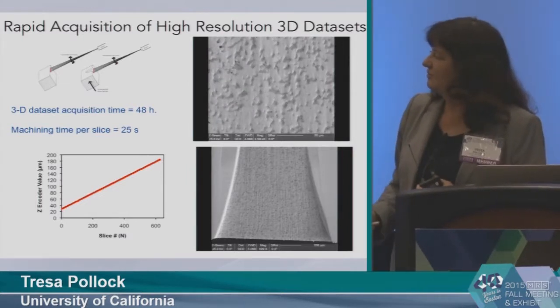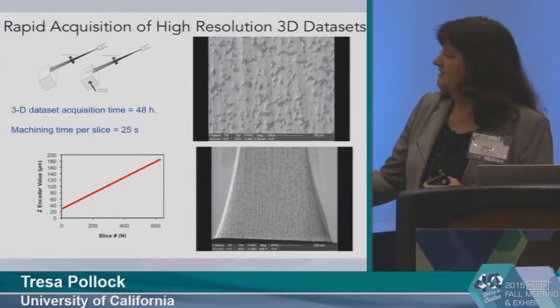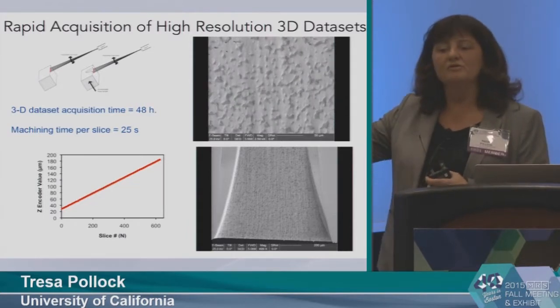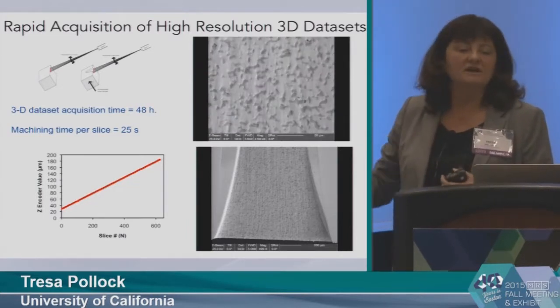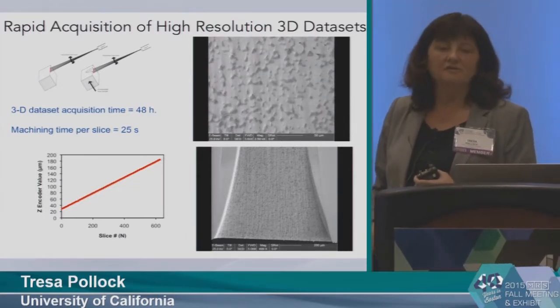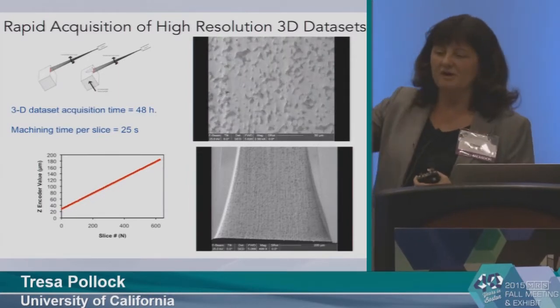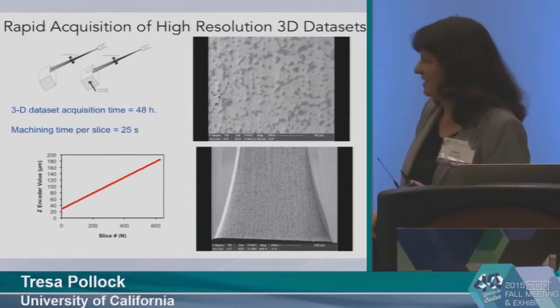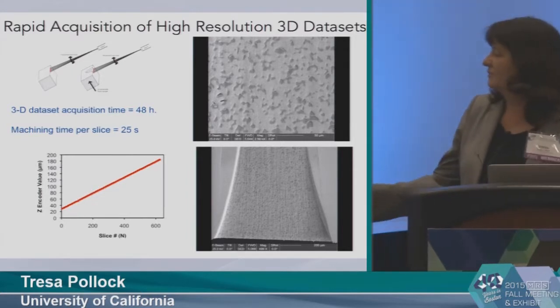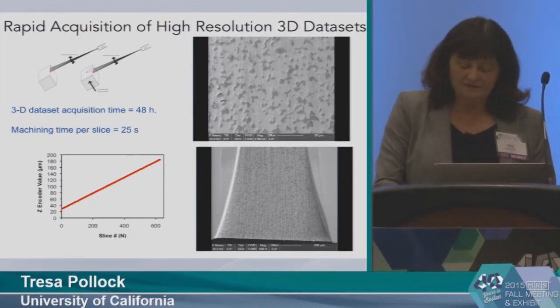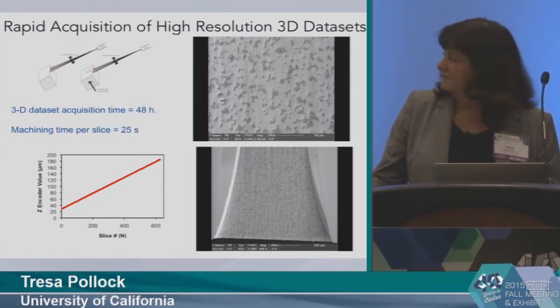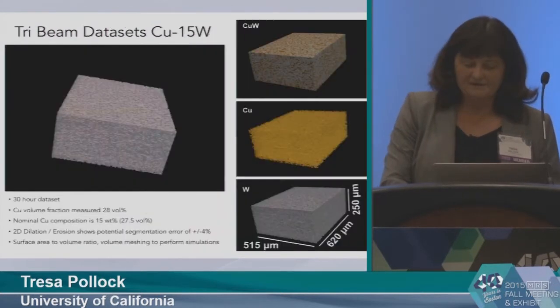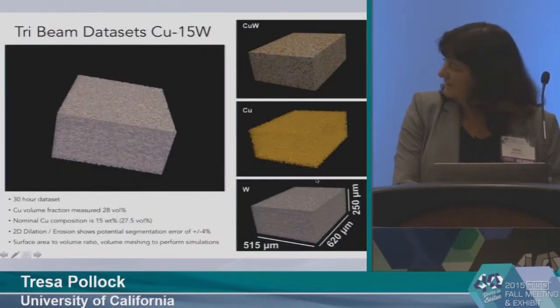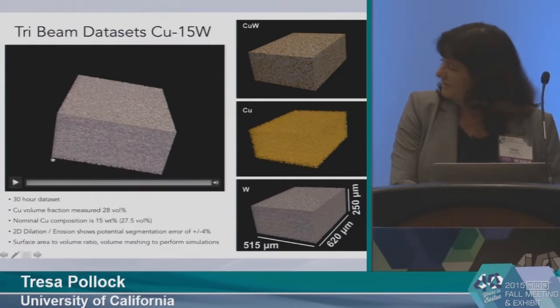You can see a few voids here. And basically, the material removal is now free. It takes a few seconds to remove the material. It, of course, takes much more time if you want to get chemical information or crystallographic information. And so you can fully automate this and get those sorts of data sets now in a couple of days. And so here, for example, is that data set, 30 hours worth of it.